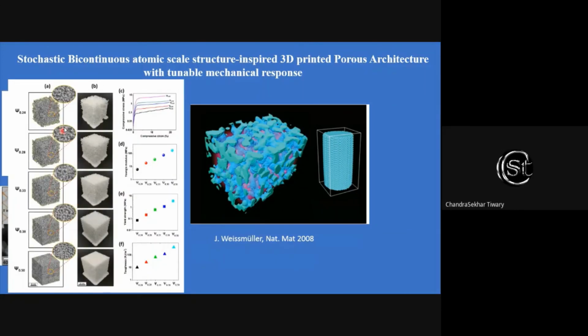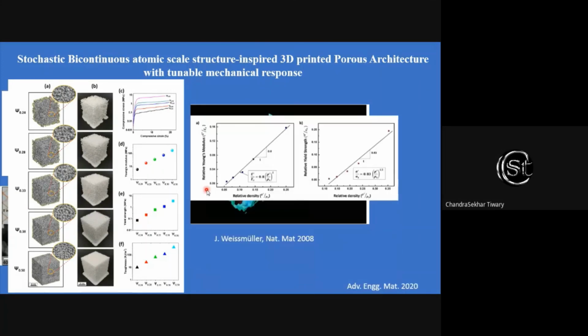And when we print different thickness, different density, we can see that the modulus and the strength can be tuned. Not just that, we can fit with the model, and if some requirement comes in a particular region for a particular modulus, we can print that particular density material wherever you need.